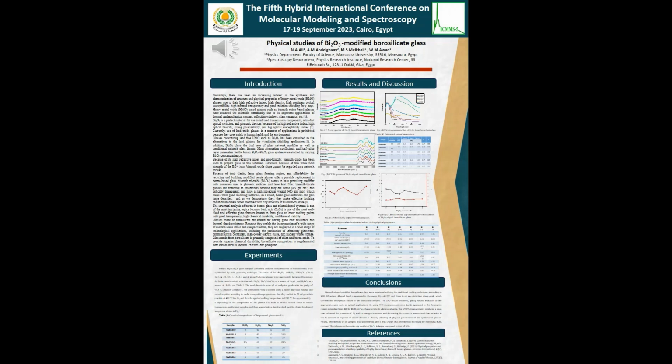Finally, the density of all samples was determined, and it was shown that the density increased by increasing Bi2O3 content. This is because the molecular weight of Bi2O3 is larger compared to that of SiO2.